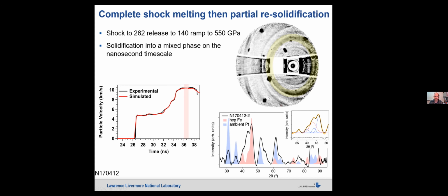And so when you do a line out, what we see, and this is shown in more detail in this line out, is a fit of an HCP triplet and a Gaussian, which we're representing as the liquid diffraction feature. And that is an excellent fit to this feature around the 40 to 45 degree 2 theta angle. And so this was actually a really important experiment to observe this mixed phase, and I'll tell why a little bit later.